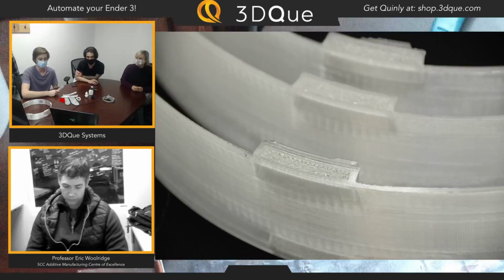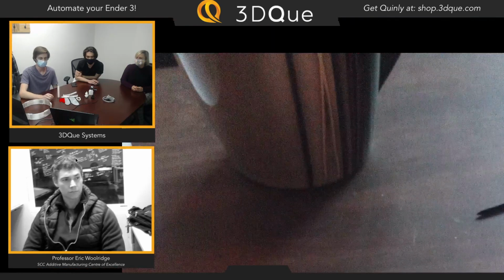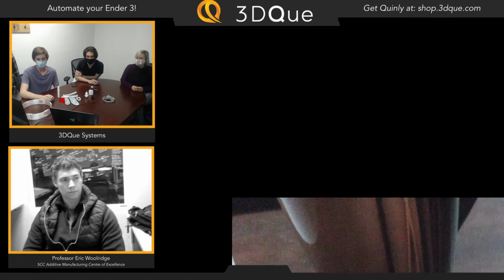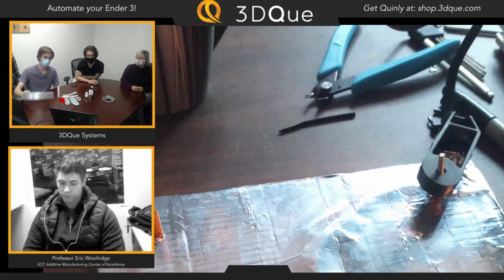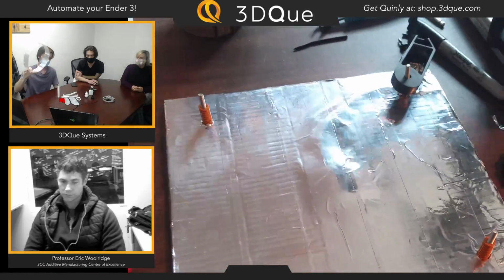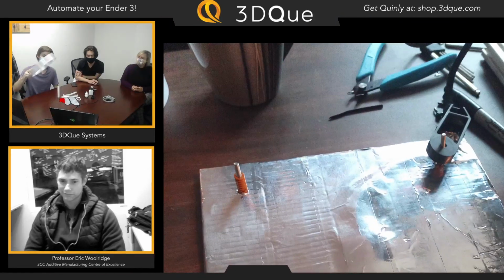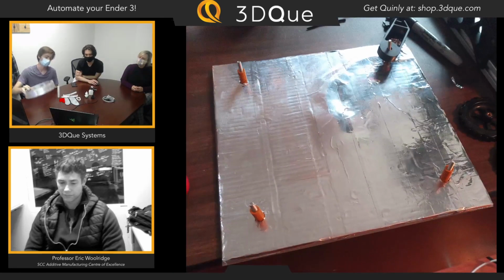I think Mateo's getting a picture up on the screen right now. Yeah. And this allowed me to go from a max temperature of 110 degrees on the bed to 140 degrees on the bed. And so these polycarbonate parts I have here, this is a filament dehydrator extender. These were all printed at 135 degrees on the Ender 3 bed using our vapor build plates.